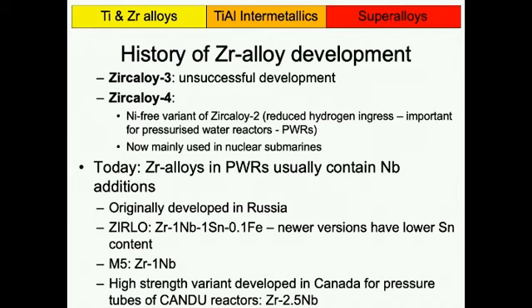it's easier. And so today, what we find is that usually modern zirconium alloys used in PWRs, not so much in BWRs, but pressurized water reactors, contain some niobium. And actually, to be fair, this was first thought of by the Russians, and then picked up by the Western world as well. So today's alloys, this one, which is called Zirlo, or a variant of this these days, with 1% niobium, tin and iron. And this is a Westinghouse product. So Westinghouse is a US, Swedish, small part UK company. M5 is a product by, well, now it's called Framatome again. It's a French company. And you can see that this is simply zirconium and niobium.